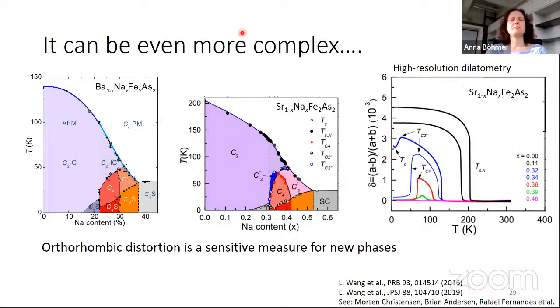Vacancies in 2D materials. Well, there's certainly a strain field associated with them, so a local distortion. When I say distortion here, I mean an ordered one, really, where the whole system is distorted in the same way. I don't think it's the same thing here. If I have a vacancy that's not ordered, that's inhomogeneous strain, inhomogeneous distortion. That's also interesting, but it's a little bit different, and I think you would not talk about phase transitions there. But I'm not an expert on 2D materials.